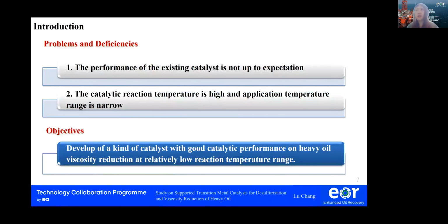However, this method still has some deficiencies. The first one is that the performance of the catalyst is not up to expectation. And the second one is that the reaction temperature is still relatively high, and the application temperature range is relatively narrow. Thus, we would like to develop a kind of catalyst which has good catalytic performance on heavy oil viscosity reduction at a relatively low reaction temperature range.